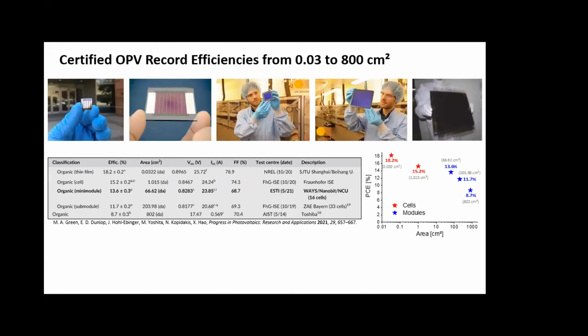Okay. So first of all, this is an overview of the current OPV record efficiencies from square millimeters to 800 square centimeters. The current record at 3 square millimeters is 18.2%, whereas at 800 square centimeters, it is 8.7%. That is a large discrepancy. And you can see when you go from 3 square millimeters to 1 square centimeter, you already lose from 18 to 15% at the moment. That's quite a lot, and both are cells.